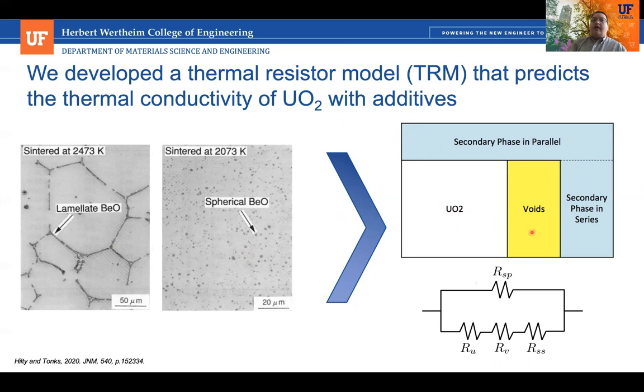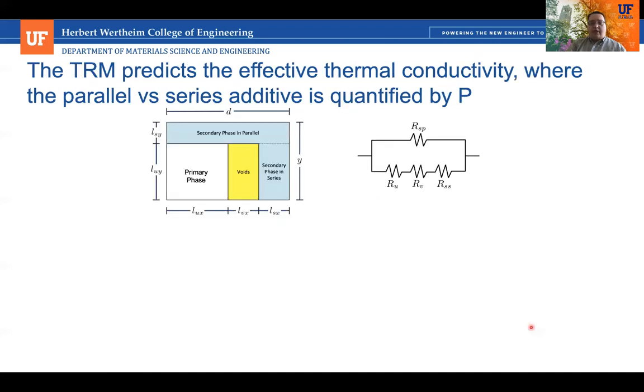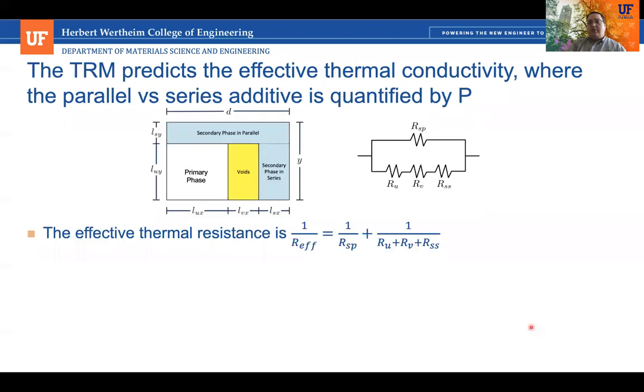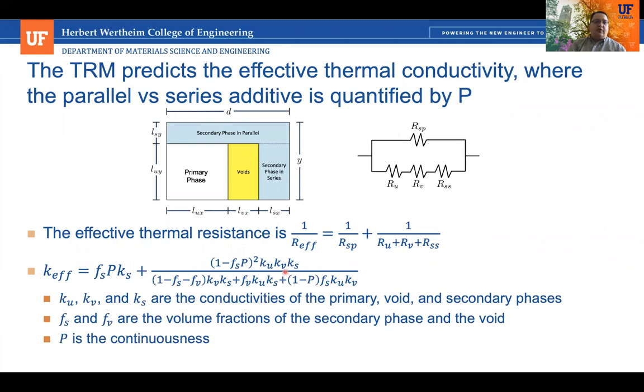And then we also might have either interfacial resistance or voids along the interfaces, and we need to account for their contribution as well. Depending on the amount of additive, either in parallel or series, we can transition between different types of microstructures. And so we end up with 4 thermal resistors. We can take those 4 thermal resistors and get the effective resistance, and then turn that into the effective thermal conductivity, and make it all a function of the thermal conductivities of the individual phases, the UO2, the additive, and the voids, and also the volume fraction of this secondary additive phase and the void phase.